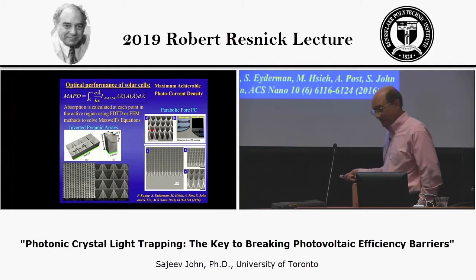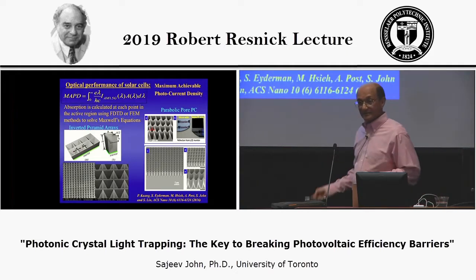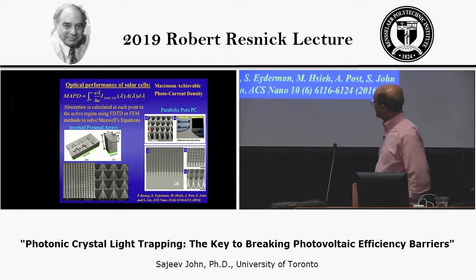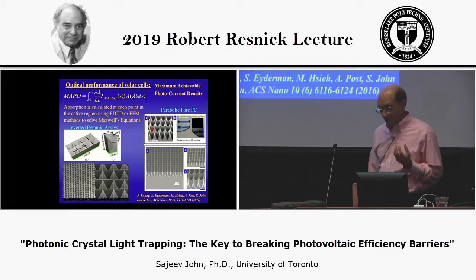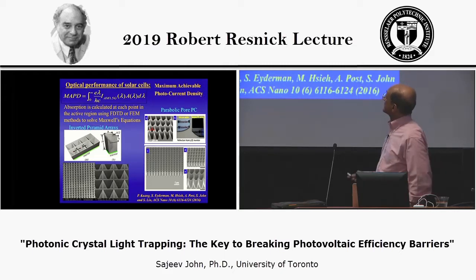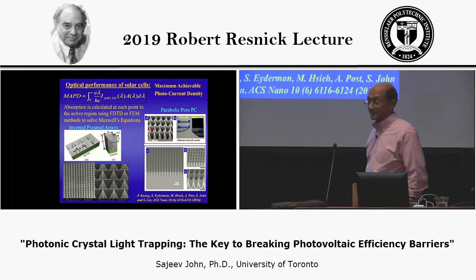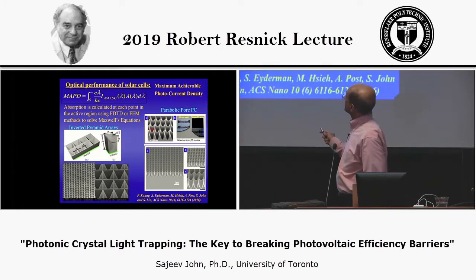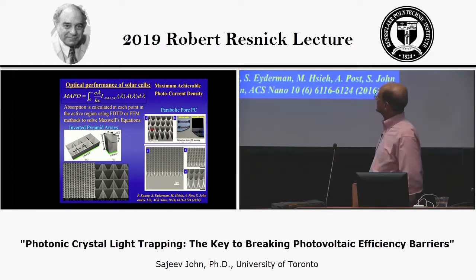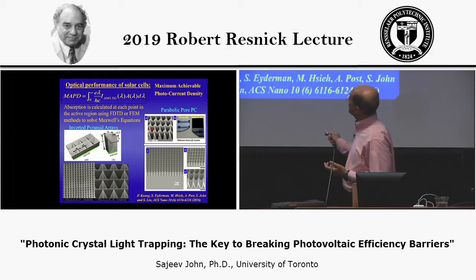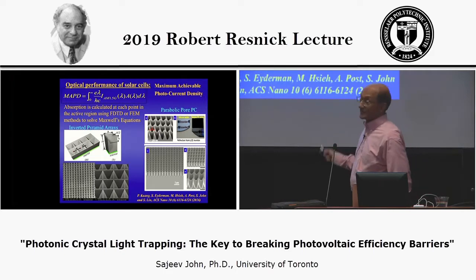And now what I'd like to go to is some of the actual structures that we have in mind for realistic solar cells and how these photonic crystal concepts enter that. One of the metrics for defining how much light is actually absorbed is referred to as the maximum achievable photocurrent density. So what it is simply the solar spectrum that I showed you a picture of earlier as a function of wavelength over this broad range. It's called the AM 1.5 solar spectrum, multiplied by the absorption coefficient of the structure that we have in mind due to wave interference effects, divided by the photon energy and multiplied by the electronic charge, which converts the amount of light absorbed into an effective photocurrent density.